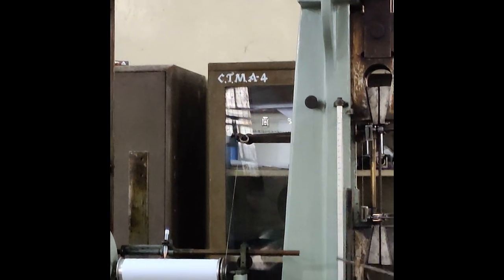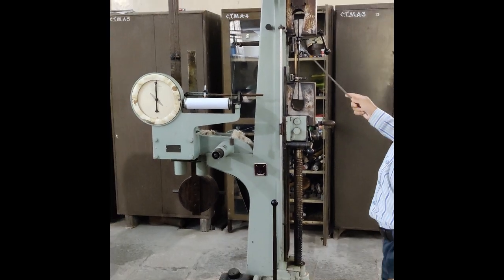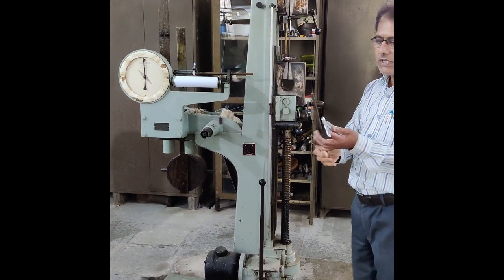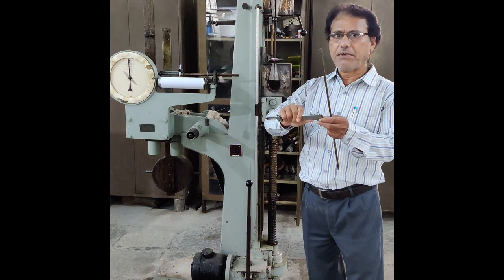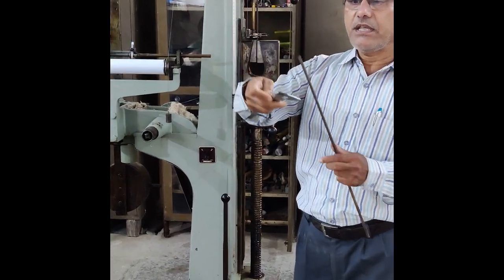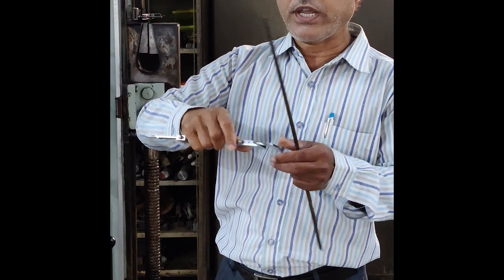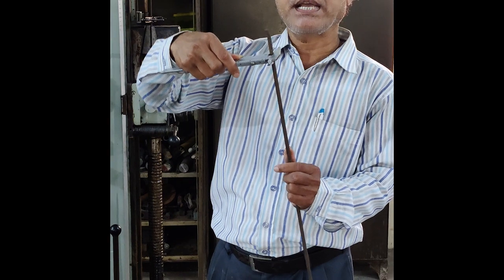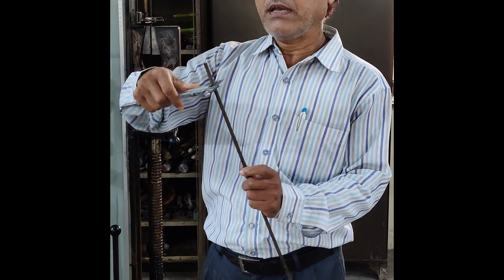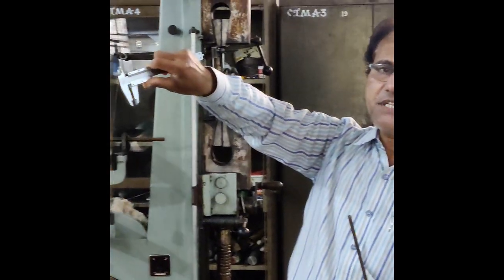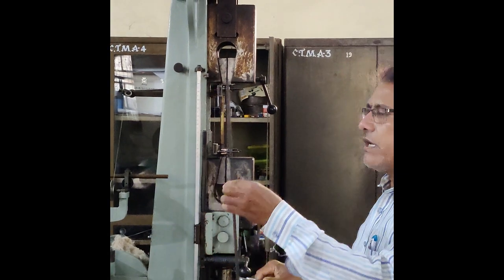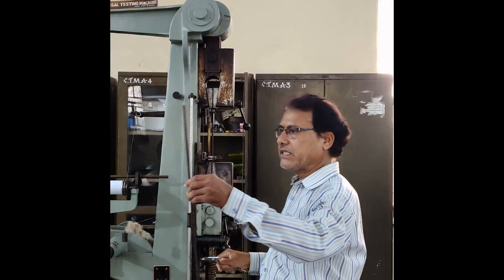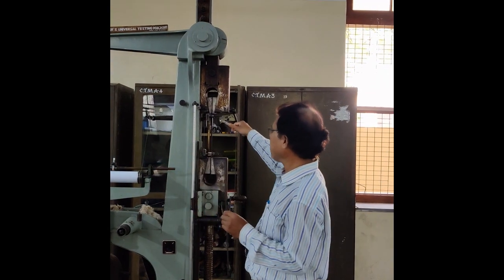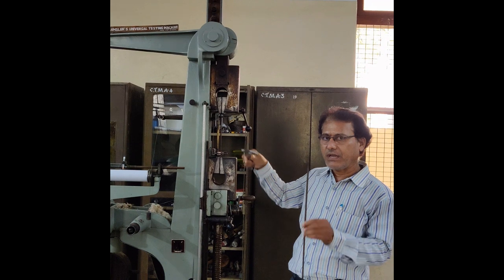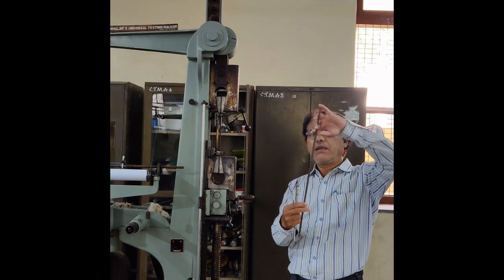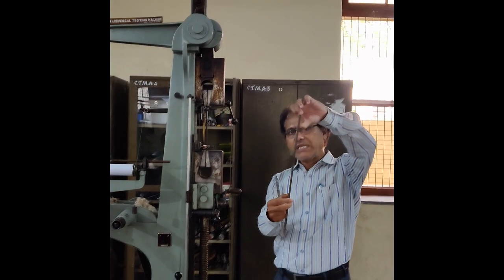Now, this is how it is in the FPS system, student. Once the specimen is given, we need to measure the diameter of the specimen using the vernier calipers. Therefore, you measure at three different locations and take that in a tabular format: main scale reading, vernier coincidence, then you will get the final reading. Take the average of these three as the diameter. Once you measure that, the gauge distance for measurement of the deformations is 20 centimeter.